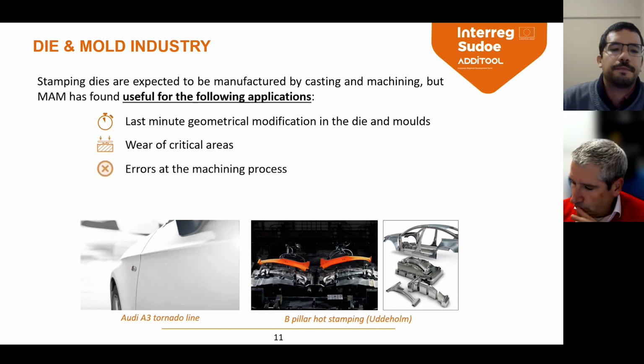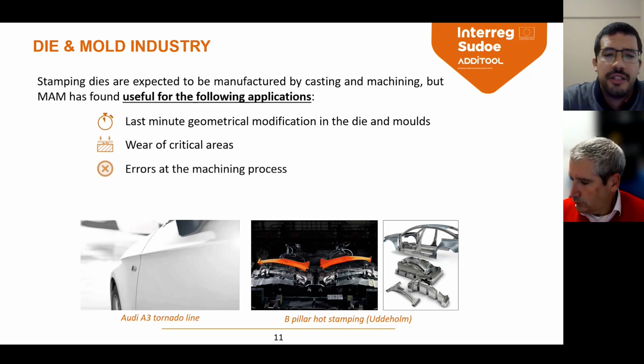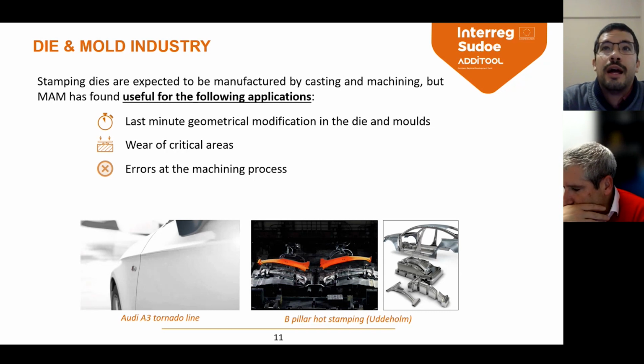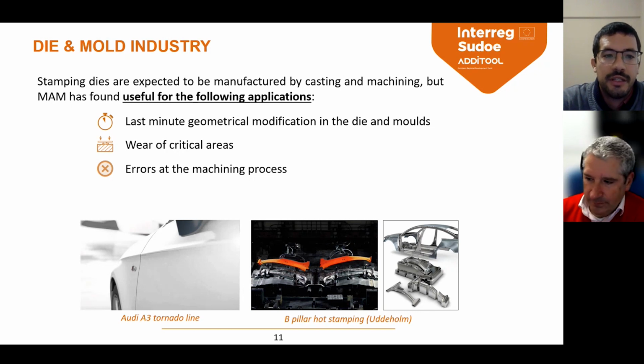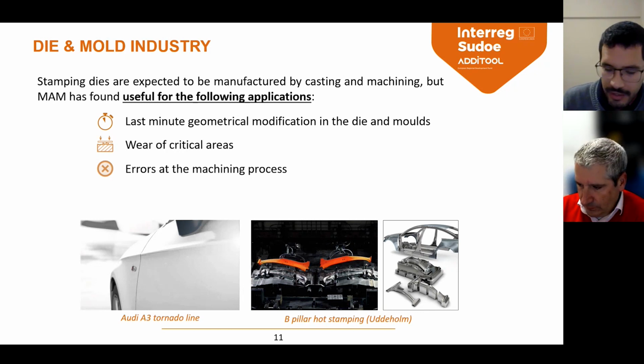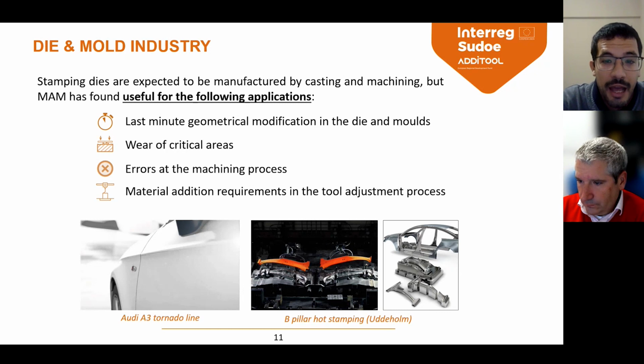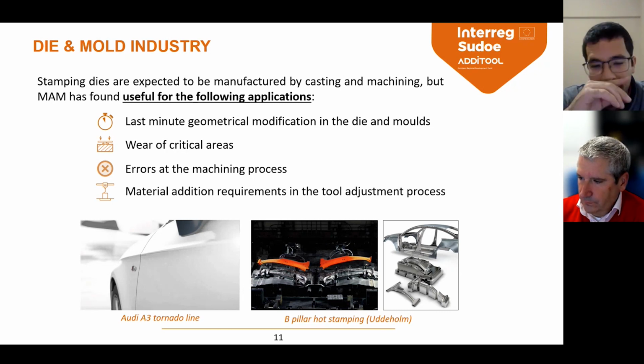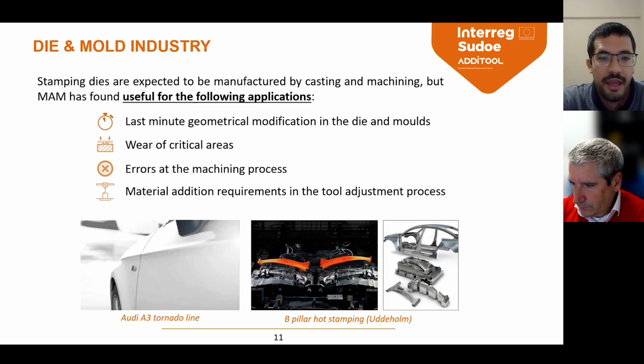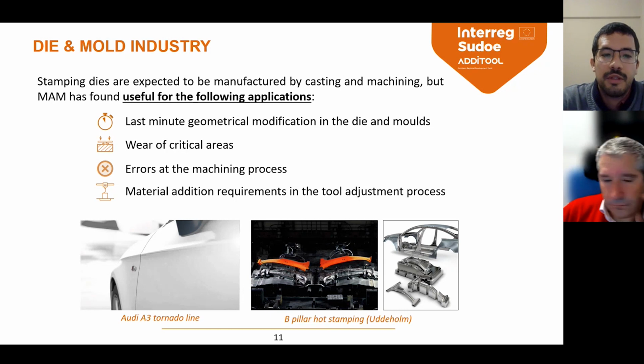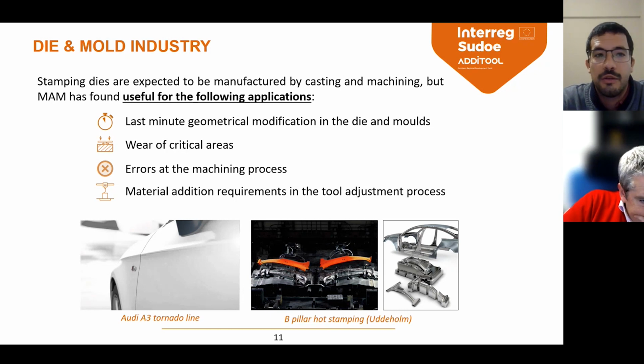Also, the critical areas that suffer a lot of wear problems could be repaired by additive manufacturing. Also, any error during the machining process, like a tool that breaks during the milling process or a wrong program trajectory, all those errors could be corrected by additive manufacturing. And finally, during the adjustment process, which is usually done manually by hand, material is being removed somehow. Instead of removing material, if it's required to add material, additive manufacturing could solve these problems.